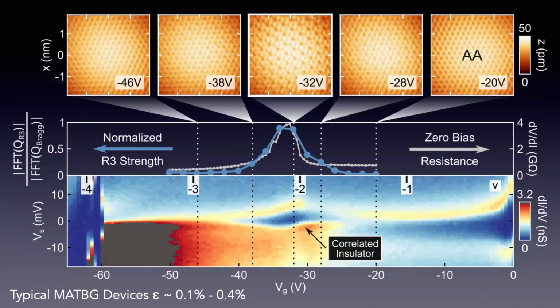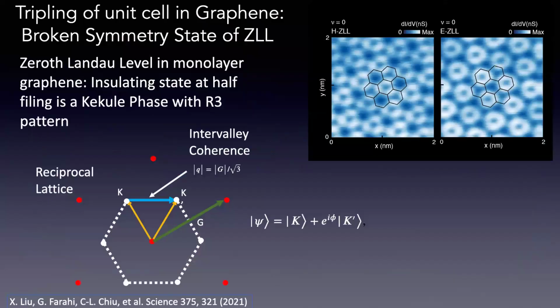So when we measured this the first time, actually maybe 3 years ago, we were like, oh, this is wonderful. We figured out what the insulator is. And the reason we thought it was wonderful is because it related to something we had studied in graphene just the year before, not in zero magnetic field, not twisted, but with a magnetic field applied to make the zero magnetic level graphene. Zero magnetic level is special. In graphene, you have 4 degrees of freedom, 2 spin and 2 valleys. And when we have filled this zero magnetic level, nice flat band, you also get an insulating state.